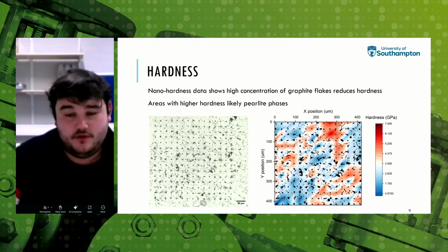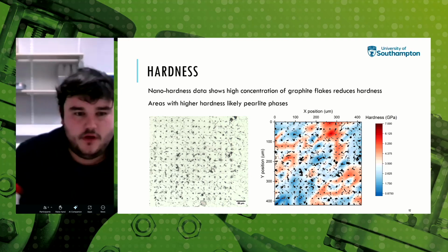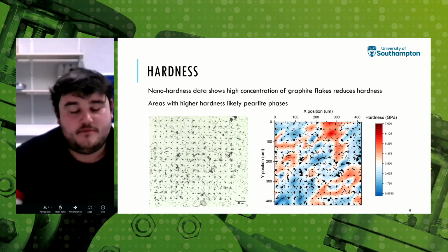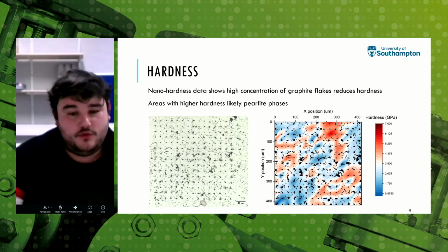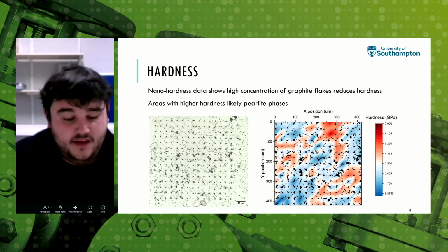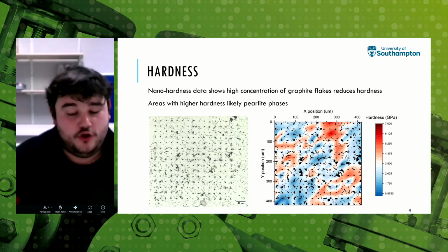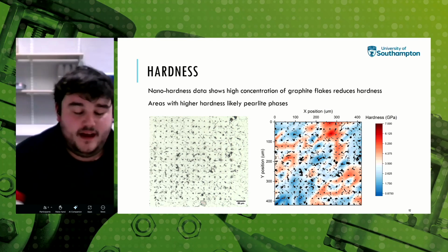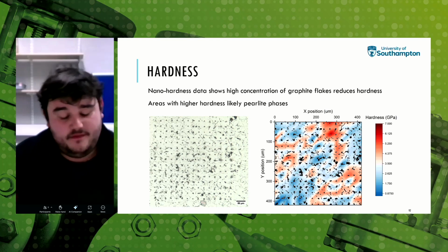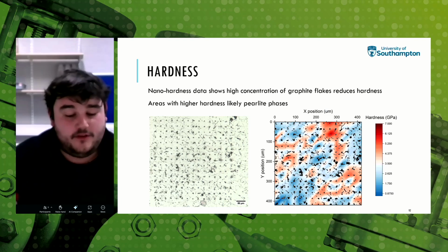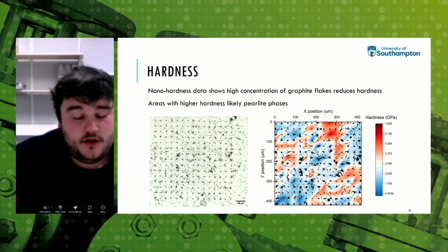And it's quite clear that in the regions where there's more graphite flakes, so the ferrite graphite regions, there's a much lower hardness than those pearlite regions with a much higher hardness. This allows us to basically draw there's two regimes in the material. Pearlite phases that are mechanically stronger and ferrite phases that are perforated with graphite flakes that are very soft. Go to the next slide, please.